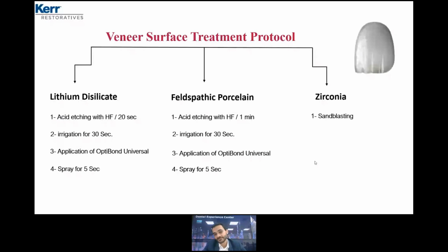I can say yes, because actually you need first to try the restoration, the veneer, in the patient's mouth. You need to check the position, the triangle, the shade, which means you will have contamination, and all of that will cover the porosity that we had before from the sandblasting. So it's better to do the sandblasting in the clinic. Irrigation, application of OptiBond Universal, and spray for 5 seconds. If we follow this protocol, you will have a successful surface treatment for the veneer.